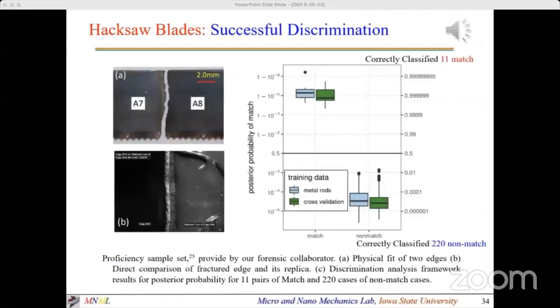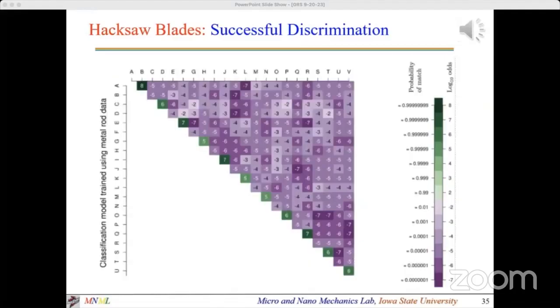These are successful applications of the discrimination framework. This is a box plot of posterior probabilities of matches for all our cases using 2 different model training mechanisms. Higher values indicate that a match is more probable. We observed that all the samples were perfectly classified into matching and non-matching surfaces at p equals 0.5, regardless of the training mechanism that we used. It plots the posterior log odds of match across all combinations of fracture surface pairs with classification model training by cross-validation. We observed that both types of training techniques result in similar posterior log odds.